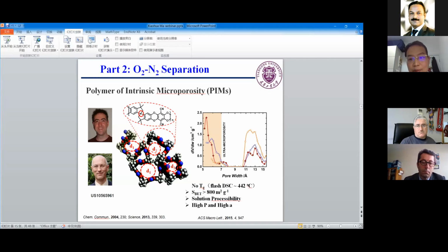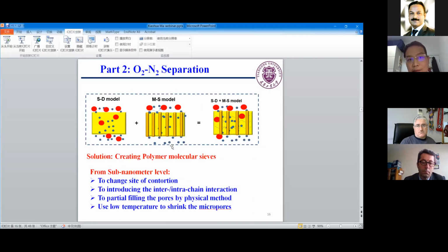permeability and modest selectivity. In this case, the gas transport mechanism is changed. In traditional polymers, it was the solution-diffusion mode, and in molecular sieve membranes like zeolite, the gas transports through the zeolite by molecular sieving. If the gas molecule is bigger than the pores of the zeolite, it will be rejected. If it is smaller, then it will transport.